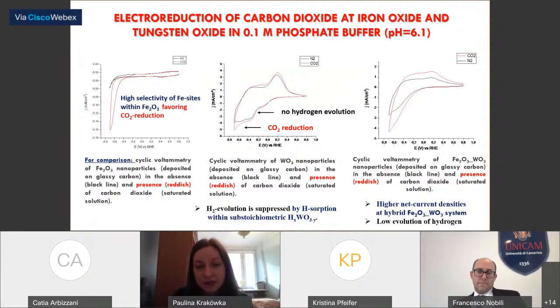Selectivity of the catalytic systems largely depends on the active adsorptive CO2 phenomena and the affinity of the catalytic centers to the adsorptive carbon monoxide intermediates, leading to their protonation or hydrogenation. In this respect, the presence of such metal oxide additives as tungsten oxide or high surface area hydroxyl group rich zirconia leads to activation and electrocatalytic enhancement effect.